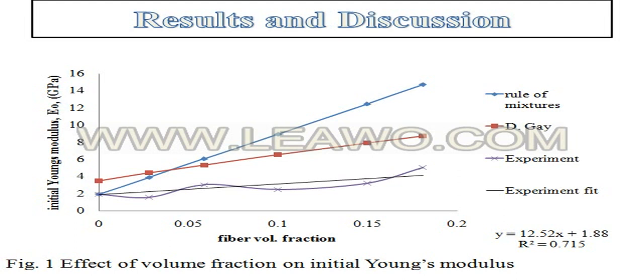Here you can see the initial modulus was plotted against the fiber volume fraction employing the rule of mixtures model, DG model and others, and you can see that the rule of mixtures and the DG model, the empirical data was fitted with a linear model, and you can see that a linear model actually gives an acceptable plot.